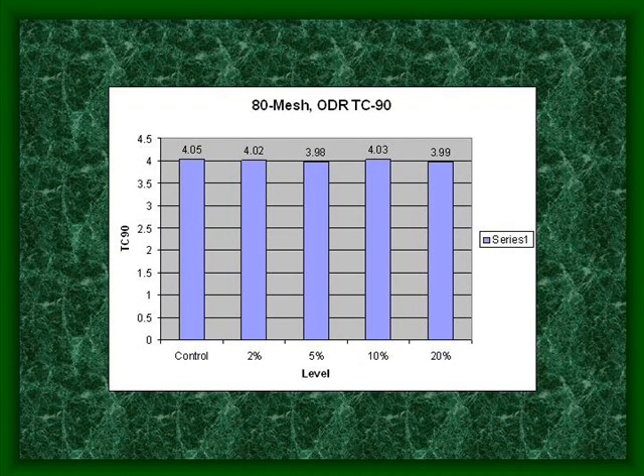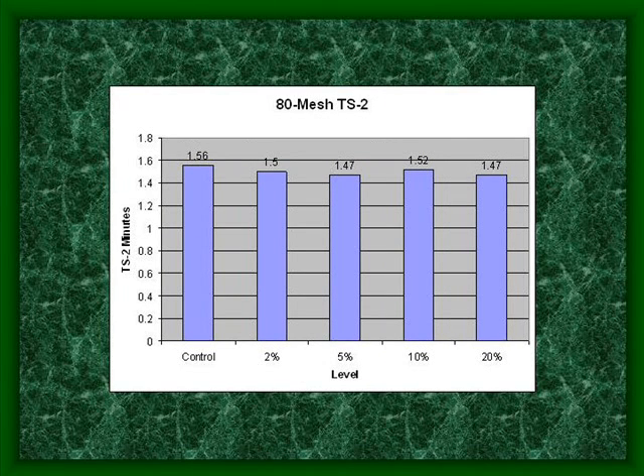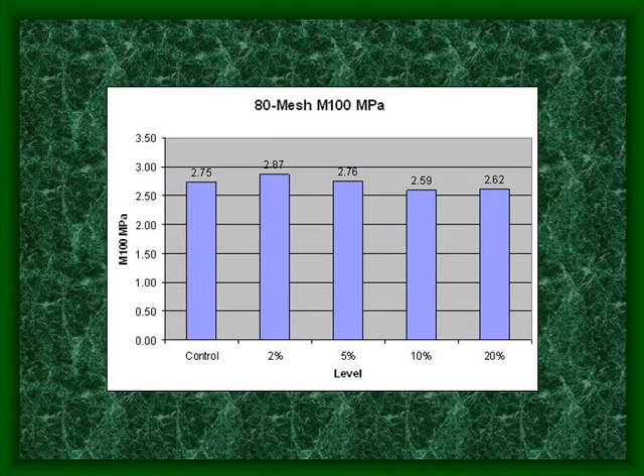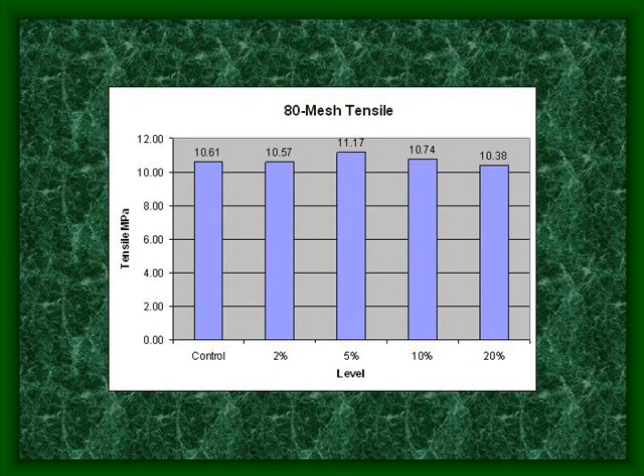The higher viscosity naturally led to slightly faster T90. And scorch values also decreased with increasing powder level. There was no significant difference in the modulus of any of these samples. And there was only a slight decrease in tensile with high loadings of the micropowder.